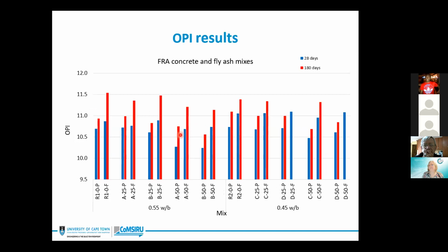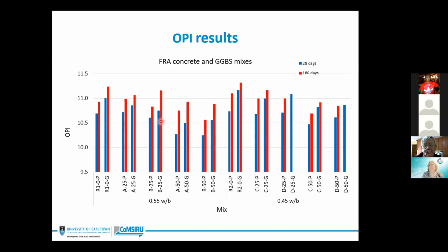So on addition of fly ash, the microstructure of the concrete mix is improved. The improvement is quite significant over a prolonged curing period, as seen from the steepness of the graph from 28 days to 180 days. This indicates that fly ash concrete may require extended curing. Whereas there's an improvement in the microstructure of GGBS, however, this increase may not be as significant as that of the fly ash mixes, particularly over a longer curing period.